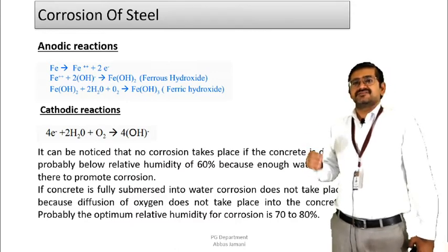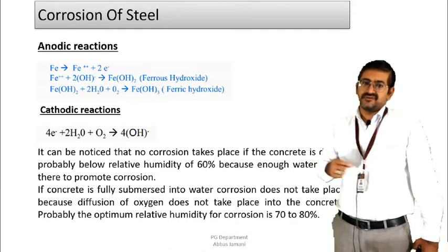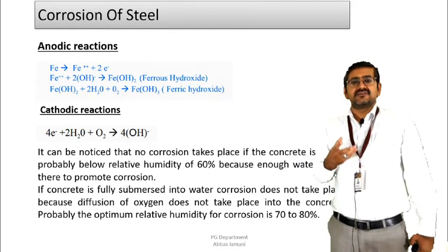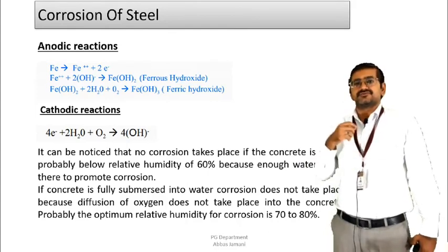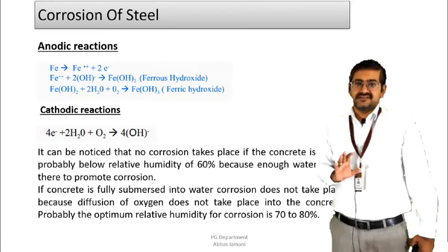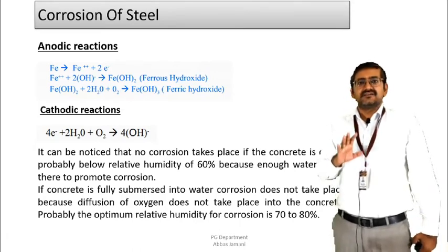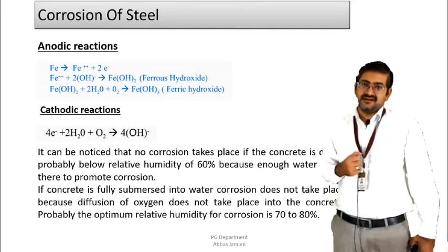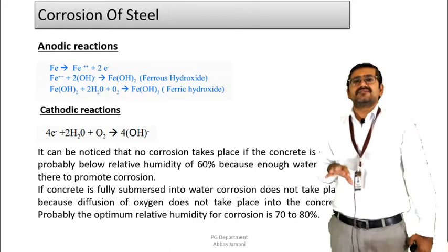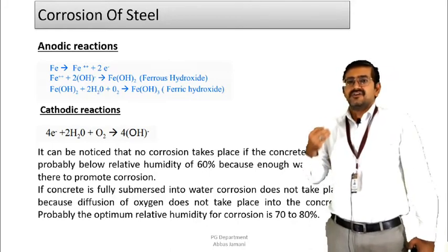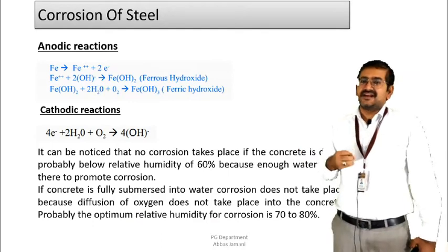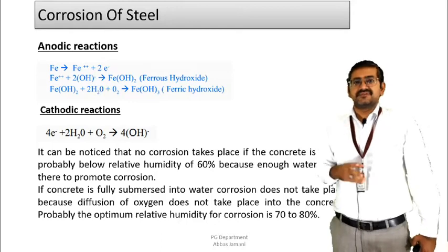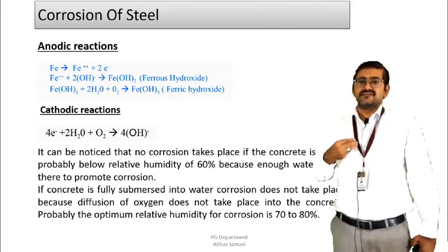Once the pH value is reduced, the initiation of different types of problems in the concrete starts. However, if the concrete is totally dry, then the possibility of corrosion is nil. And if the relative humidity in concrete is also around 60%, then the possibility of corrosion starting is going to be very low. Similarly, if the reinforcement is fully immersed in water, the possibility of corrosion is also not significant.